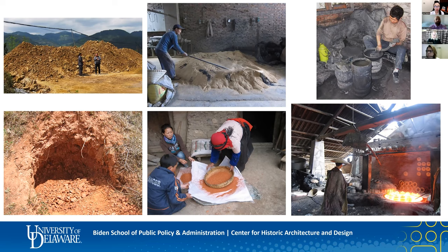And while the highest temperature achieved is important, there can also be variations in the length of time spent at the highest temperature, and then in the rates of ramping up the temperature and cooling down. All of these factors can change the internal structure of the ceramic, as can a long period of use and burial. So if we try to account for all of these factors and combinations of factors with replication in the laboratory, we'd be talking about an enormous number of samples to prepare and analyze. So really the best we can do is to pick out what we think are the most important things to vary, and then get a general sense of how those affect the micro-CT and image analysis results.